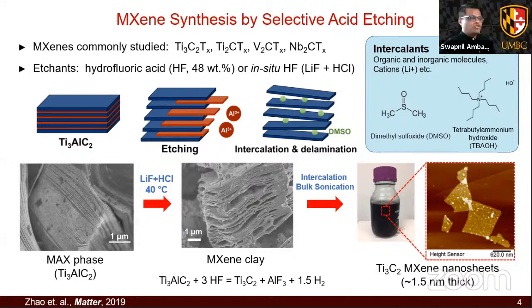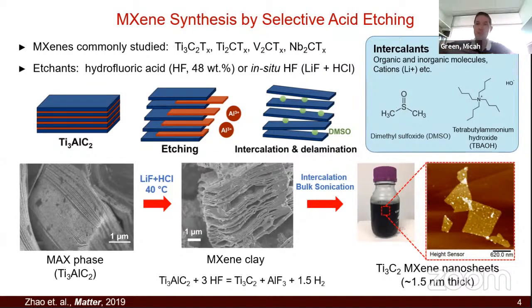So the primary reaction is with the core, or it starts with the functional groups? I mean, these things are only five atoms wide, so it's not the core. It's with the surface titanium layer, but the functional groups have an impact. They do have an impact on the ability of the water to attack the titanium and make TiO2. But it is that outer layer of titanium. Yeah. Thank you.